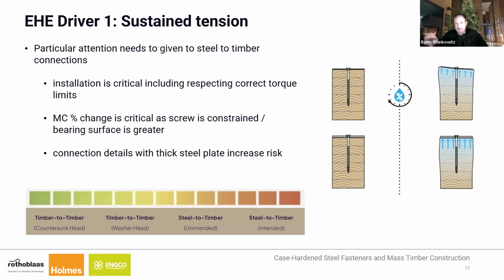The thinner steel plates on the top right, you can see some of the screw manufacturers have done some testing and found that using thinner steel plates, the steel plate will yield, and the sustained tension on the screw that is building up because the timber swells below is not as high as compared to a thicker steel plate, which is not yielding and obviously capturing more of the increasing and swelling timber below it.